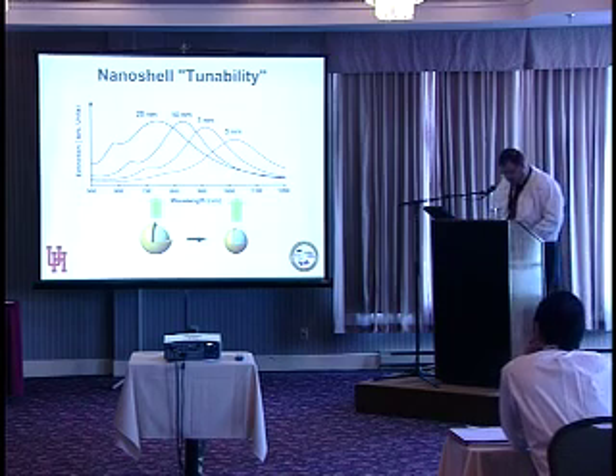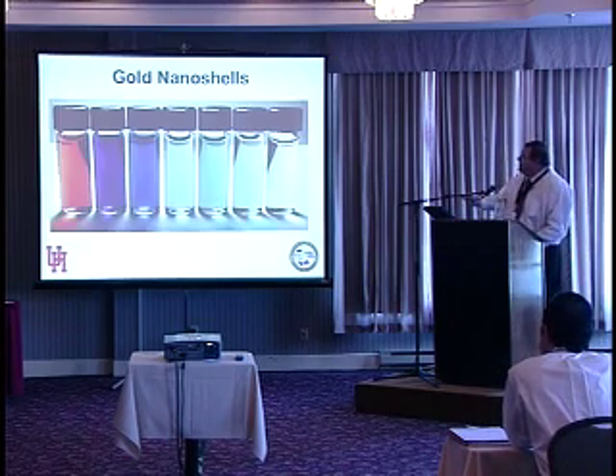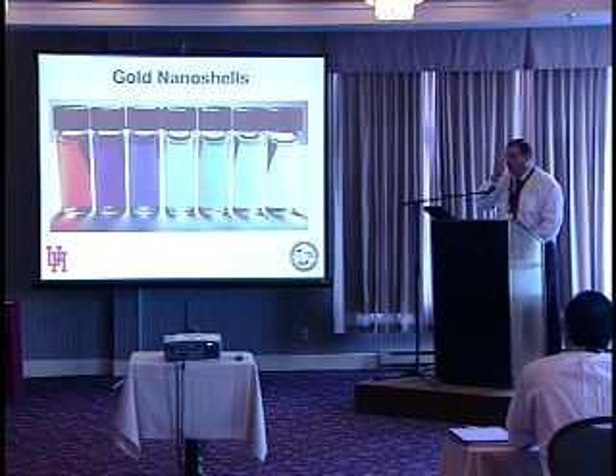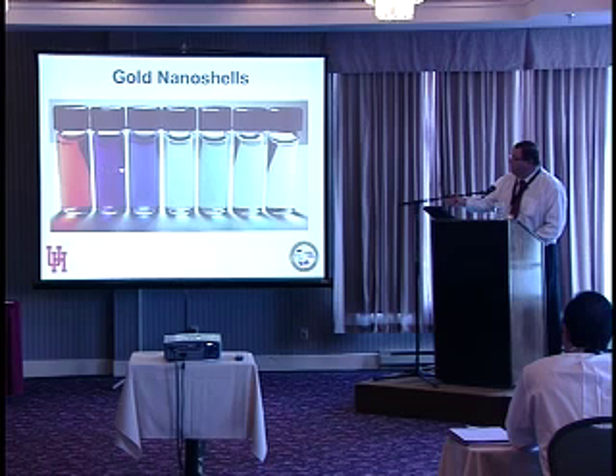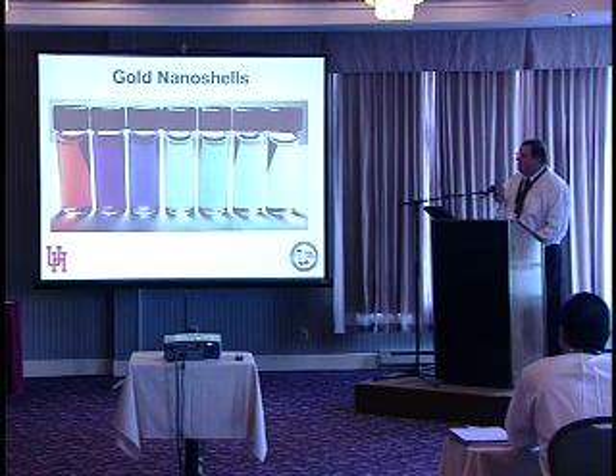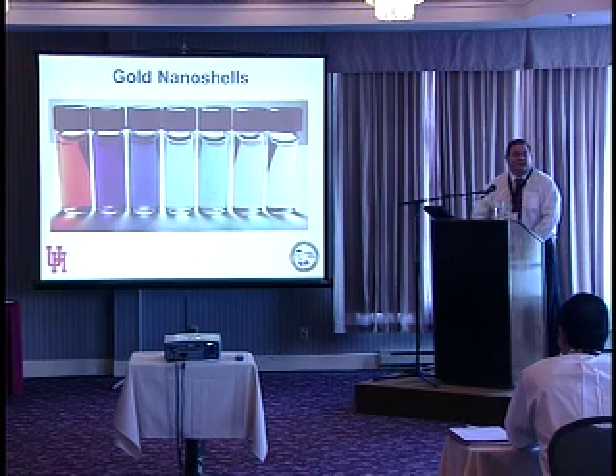So here is a slide showing you these particles. Here are some nanoshells with a thick shell, and as we make the shell thinner and thinner and thinner, you can see the color changing, and then when we're absorbing in the near infrared, it appears clear, okay?